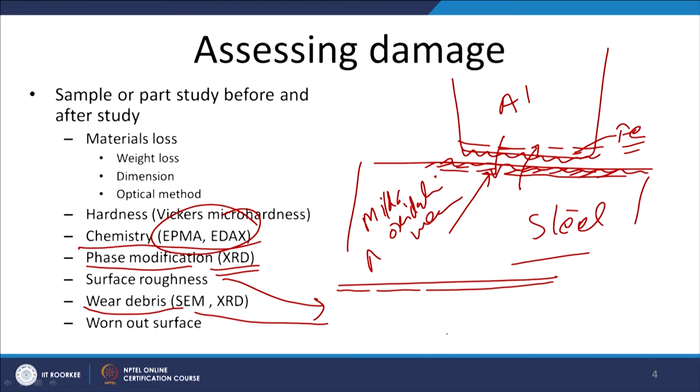are produced during mild oxidative wear. This means mild oxidative wear produces mostly metal oxides. So, the presence of metallic particles or metallic oxides is what can be confirmed through XRD analysis and scanning electron microscopic study of the wear debris.